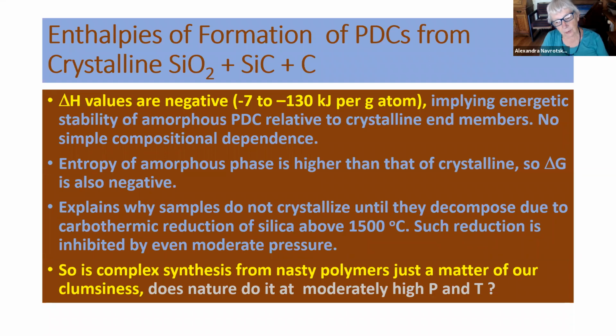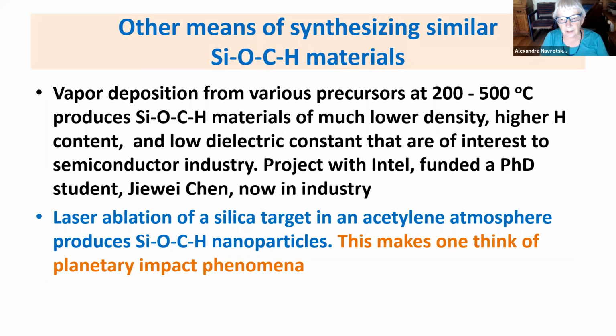So what we realized is that these materials are not just an accident of synthesizing metastable materials. They probably, in fact, have a thermodynamic region of stability, and that is something that we've been working on. So the complex synthesis may just be a convenient way to get at these materials. Perhaps there are other ways of getting at them. And indeed, one of the things that we found was to synthesize similar materials at much lower temperature and with higher hydrogen content. One can make low dielectric constant silicon, oxygen, carbon, hydrogen materials with a lot of hydrogen in them. And these are of interest, for example, to Intel, and we've had projects looking at them.